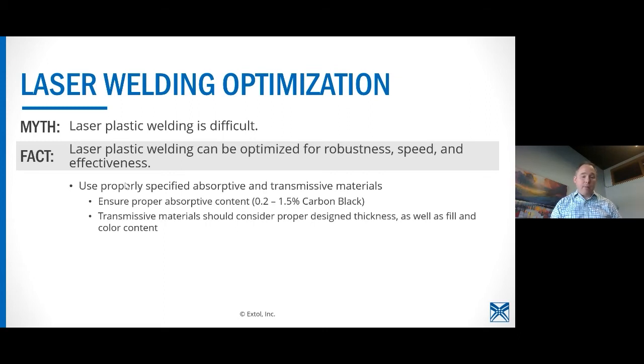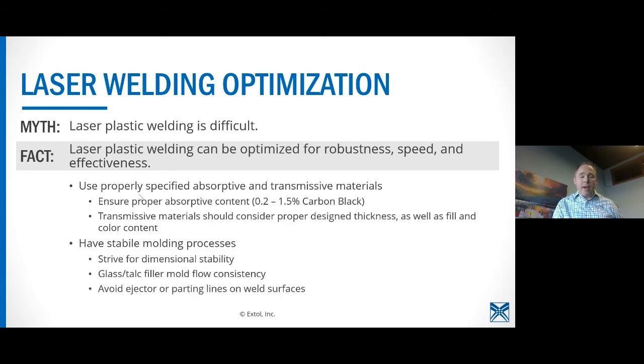it's either that the proper absorption content isn't there, 0.2 to 1.5%, usually carbon black from an absorptive standpoint is what is ideal. And sometimes we see higher, sometimes we see lower if it's a film per se. But then also the transmissive materials should consider proper design thickness as well as fill and color content. And we have actually seen, before I move on to the next one, customers that aren't necessarily controlling this very well really struggle, especially with respect to absorptive content. So making sure there's good control of that definitely helps to make that an easier process.